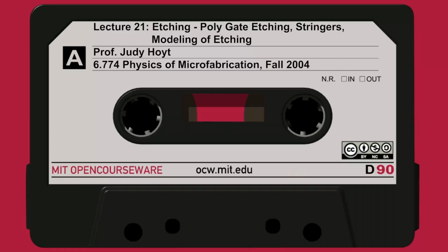In fact, that's exactly how spacer layers are formed in modern MOSFETs. The polygate is etched vertically, a certain thickness of nitride or oxide is put down, it's etched anisotropically, and you end up with a sidewall spacer. So stringers, so to speak, are not necessarily bad. Usually the word stringer means something left behind that you don't want. But if you do want it, you call it a sidewall spacer.